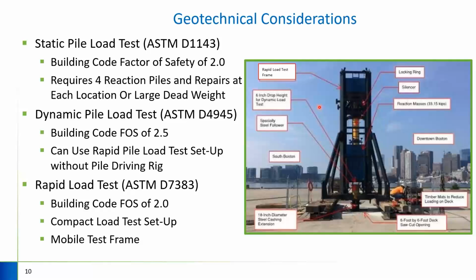And so for the static pile load test, we saw that our typical factor of safety was 2.0 per your usual IBC. But one of the main factors that led us to not use static pile load testing was that we would have to either include 4 reaction piles, which would consist of demoing out the deck at 4 additional locations for each test pile, or use a large dead weight across the entire structure. And so due to both cost concerns with having to remove additional sections of pier deck and time constraints potentially with that as well, we determined that static pile load testing was not proper for this project.